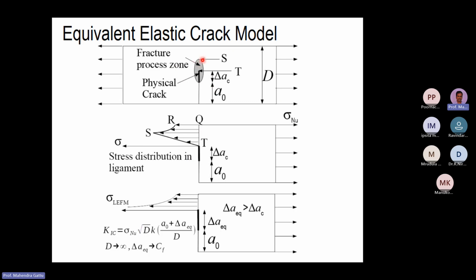All the fracture process due to the physical crack and the fracture process zone, we are lumping into one single physical crack of delta A eq, and beyond that we use the LEFM criteria. So the formula which you have developed for LEFM is applicable. The fracture toughness KIC is sigma nu square root of D K of a naught plus, instead of delta AC, which was the actual physical crack, we have delta A eq, the equivalent crack length. So a naught plus delta A eq is called the equivalent crack length, hence the name equivalent elastic crack model. We'll use this equation to analyze the experimental data.